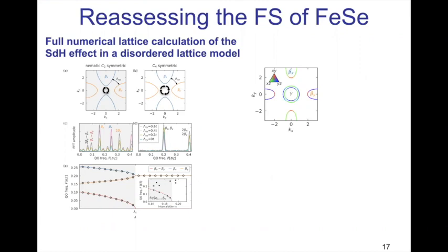The only question now is whether there is a possible mechanism which would generate this sort of interband coupling between our electron pockets. First, I want a coupling between these two pockets, because these are the electron pockets. What I don't want, because it's not observed in experiment, is a coupling between the pockets at gamma and these beta pockets.